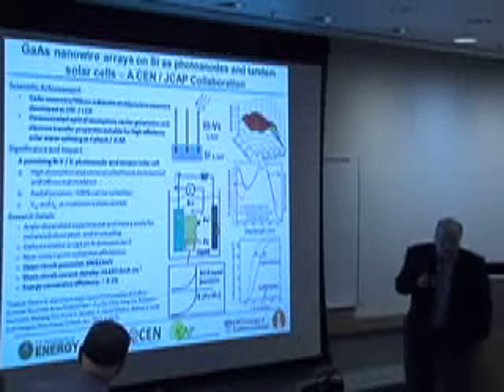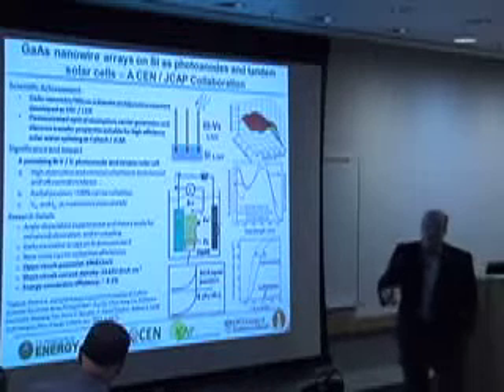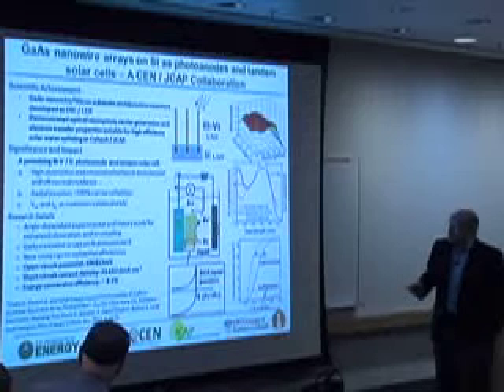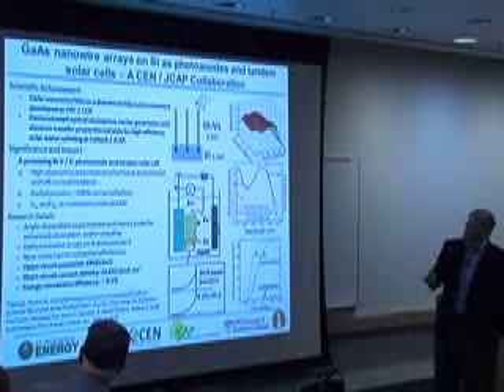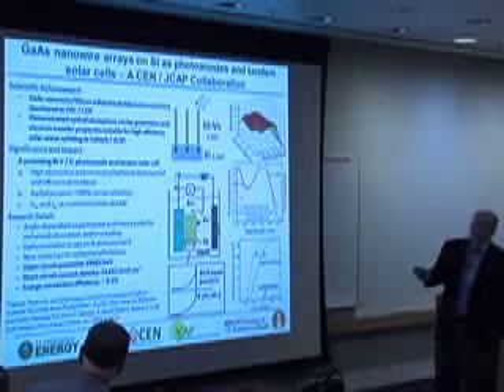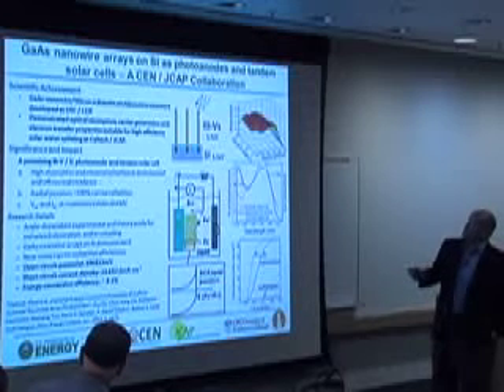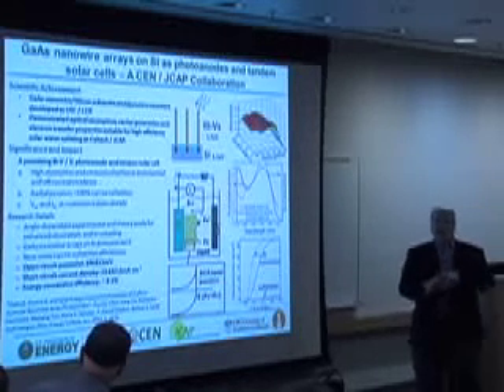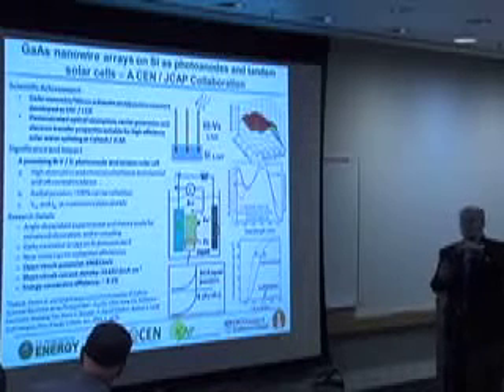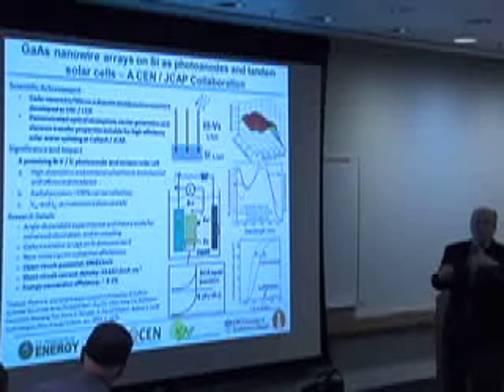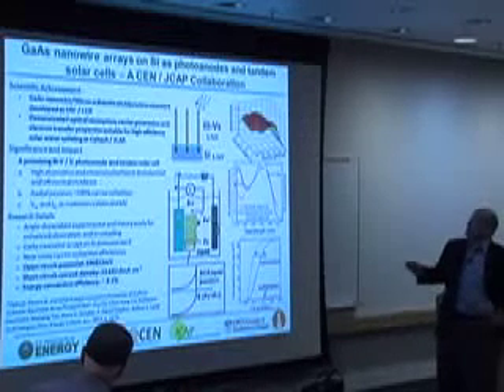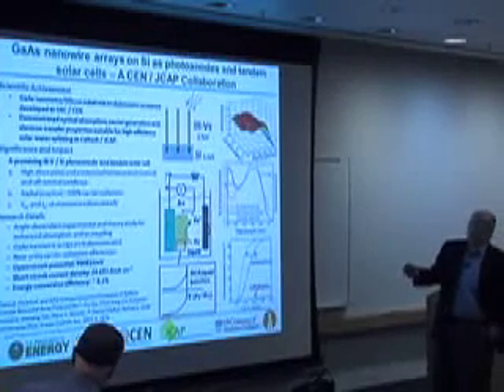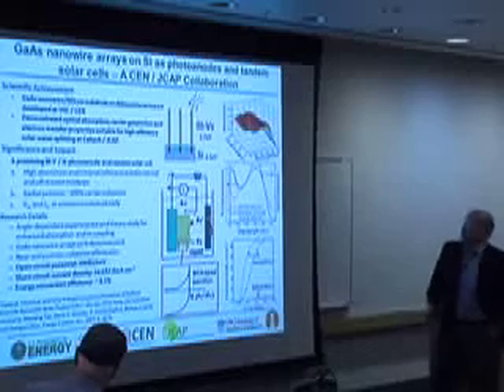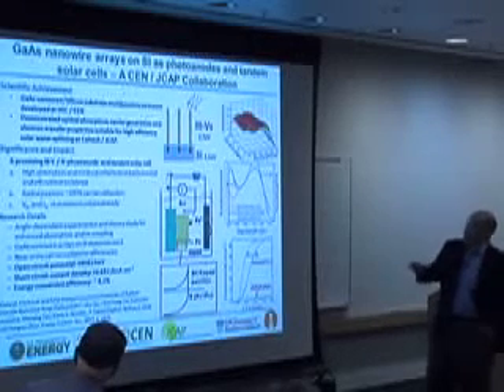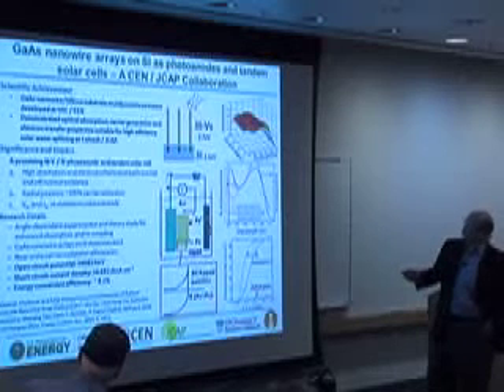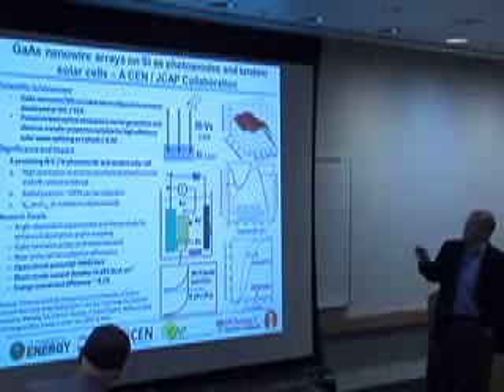So part of what we do, in addition to our own work, is we're collaborating with the JCAP Center at Caltech and Berkeley. This is the Energy Hub, where they're trying to do artificial photosynthesis, and basically they're trying to break water. They need a junction device that has an output voltage of greater than about 2 eV in order to break water. And so they're looking at integrating gallium arsenide with silicon to get the right voltage that they need. They've looked at some of the materials that we've grown at USC. In fact, one of their postdocs, Shuhu, works in my lab.